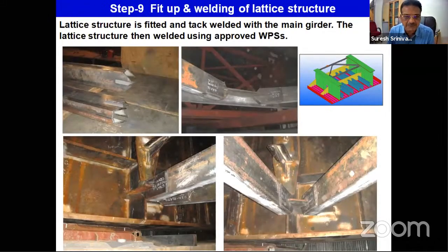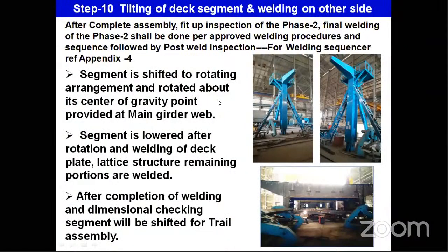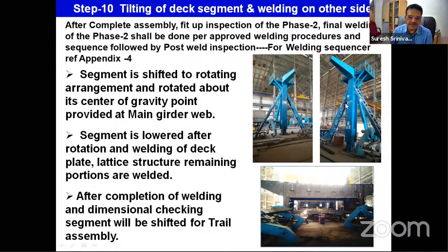So now we are coming to the assembly, fit up of one segment with another. So one segment of 68 tons is now assembled with another 68-ton segment. And you are also seeing we locked the entire structure using the lattice structure, which is again a box section structure, as you see from inside the bridge. This is already tilted upside down in this case. Now for tilting, we again fabricated a huge A-type crane, both cranes, now lifting and tilting upside down. Because remember, the deck plate are only one side welded by semi-automatic welding. After tilting, we back gouge completely and re-weld with semi-automatic welding to see that full penetration welds are made.